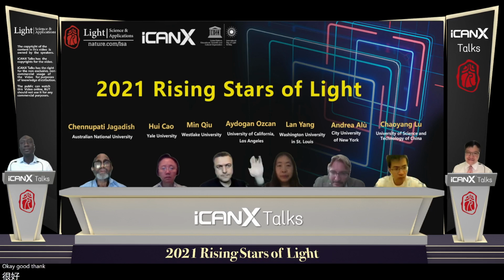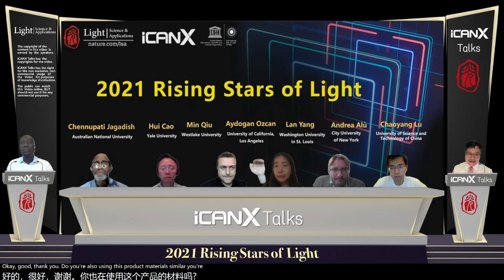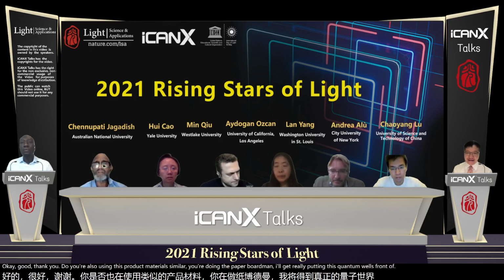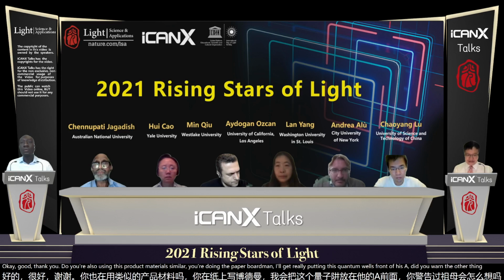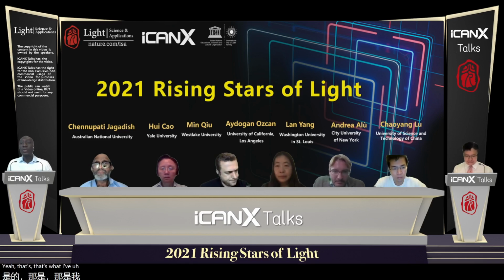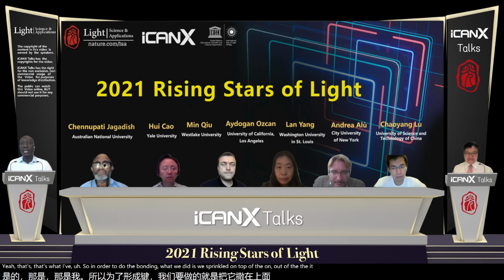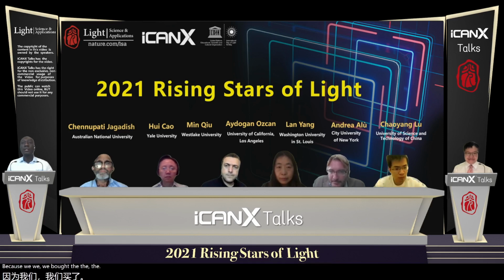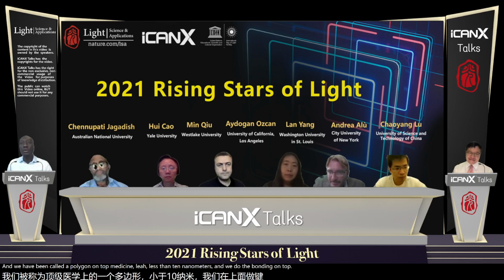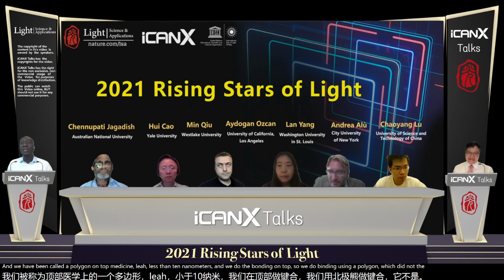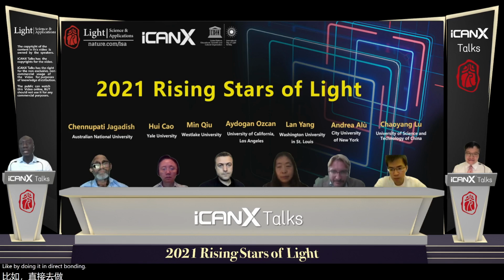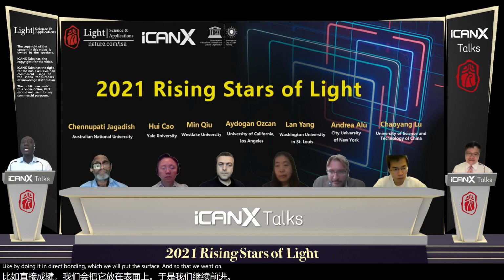Okay, good, thank you. You're also using disparate materials and doing wafer bonding. How are you really putting these quantum wells onto this GGG and YIG and other things? So in order to do the bonding, we spin coat on top of the YIG material, because we bought the YIG material on top of the GGG, a polymer, a very thin layer, less than 10 nanometers, and we do the bonding on top. So we do bonding using a polymer, which is not the fairest method. It's the industrial way. We should do it by direct bonding, where we treat the surface, so that we don't have any interlayer between them.